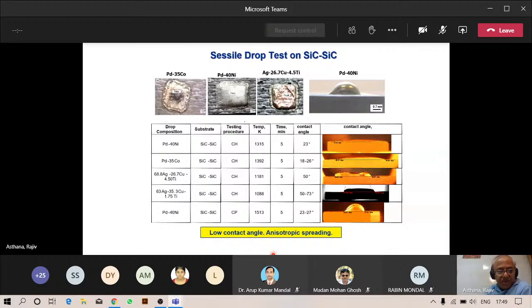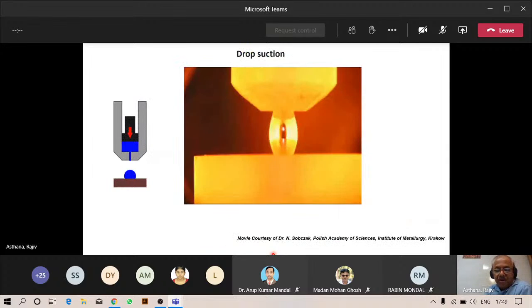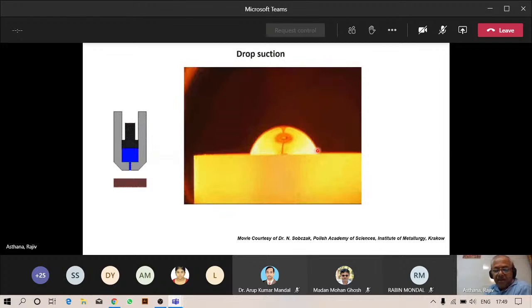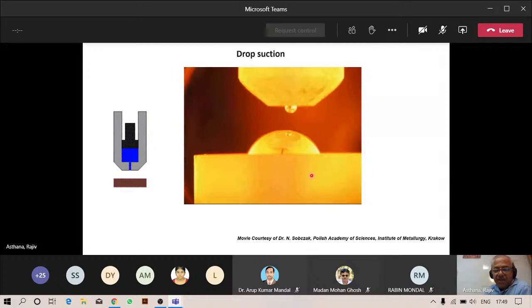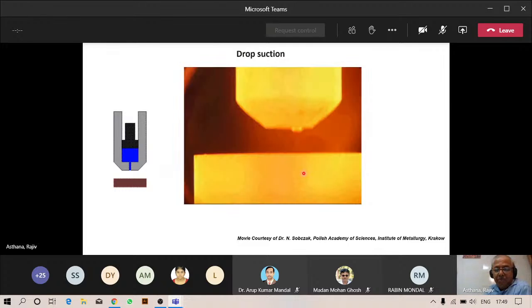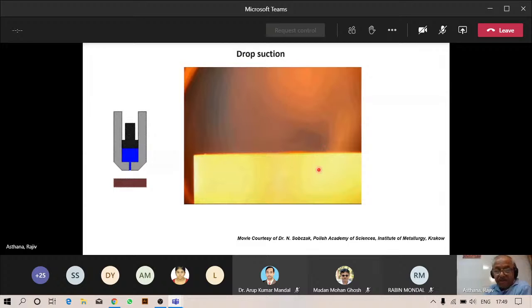We also do a droplet suction kind of an approach where you have a droplet first in contact with the solid, and then you actually suck it to open up the interface after a fixed amount of time. So you will see the droplet being removed to open up the surface here. This allows a very controlled amount of time for interaction of the surface, and that can be examined after cooling using analytical microscopy and other methods. So droplet suction was also used for some of our systems.